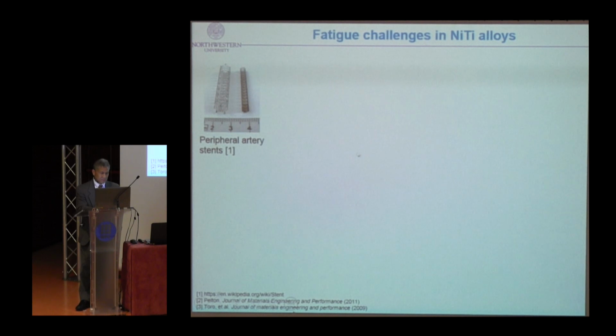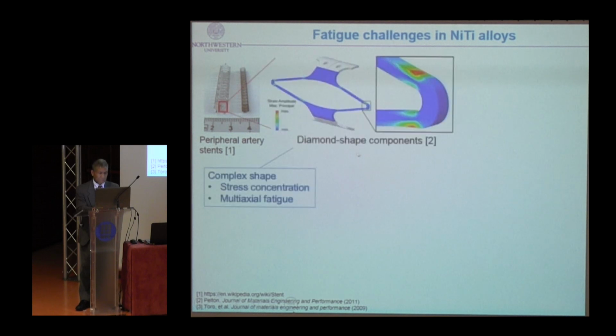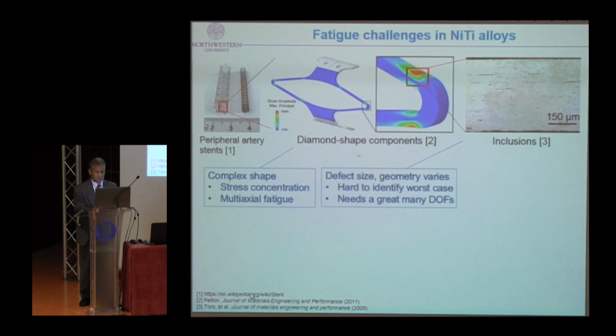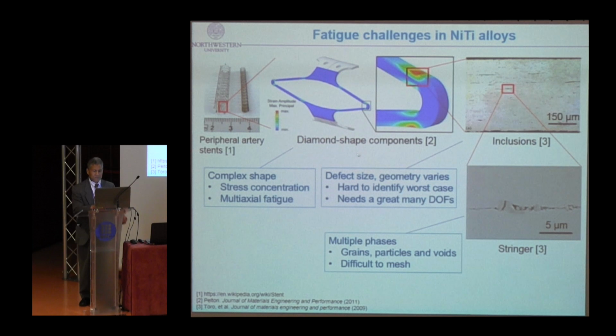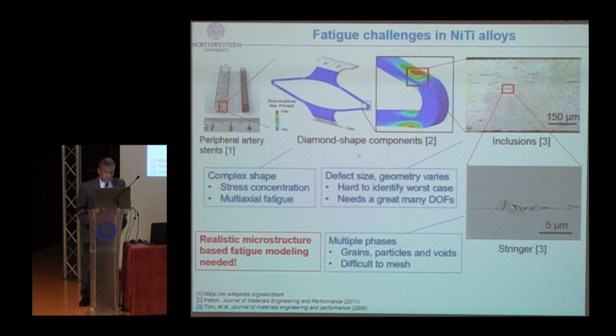Let me give you an example of what it means here. That's a typical stent, and it's a very complex geometry. We assume in this region, this is complex shape, stress concentration, multi-axial fatigue. When you go down, you have a lot of defects. When you go down further, you have something called stringers. This is based on manufacturing. So basically, you need to simulate all this process and look at how to look at the incubation period, how to predict fatigue in this case. So it's a very complex problem. And you really need to do realistic microstructure-based fatigue modeling.